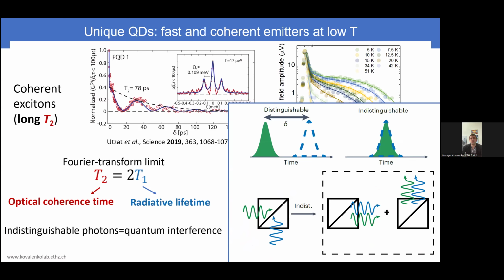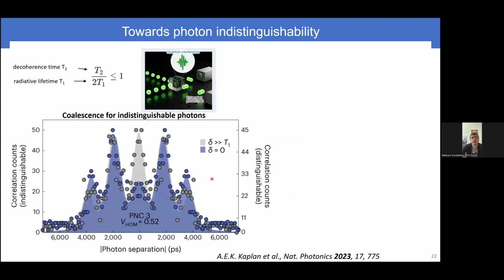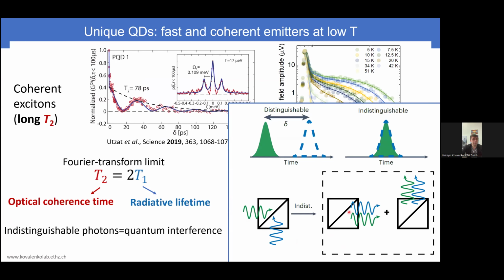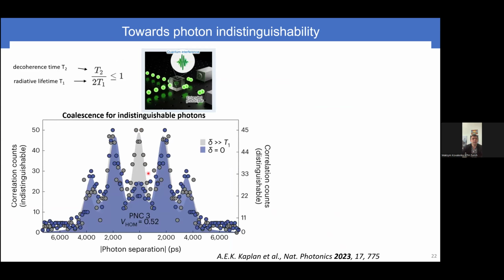And here, this is actually a figure from the paper by Moungi Bawendi, who studied many of the single dots in this two-photon coalescence experiment. And obviously, if that is the case, that there is coalescence, then they must exit on one or the other beam splitter and not in a statistical manner. So basically, you compute the theoretical pattern, the gray one, which is fully statistical, and the one with two-photon coalescence, and the amount of this dip is a measure of how much of that indistinguishability you do observe. And for very good single photon sources, like in the specific case of epitaxial dots, this goes well above 90%. And now with colloidal quantum dots, for the first time, we could see that happening in the lab of Moungi Bawendi. Three dots were reported, and this is just one of them.